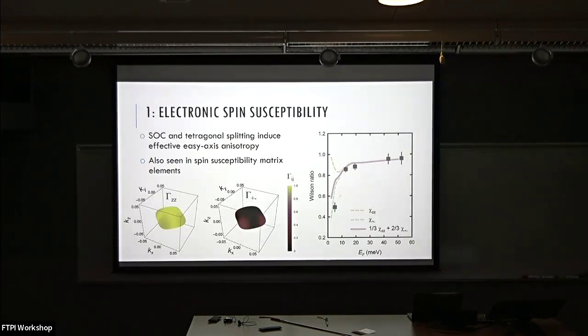Okay, and also you can see this in a very nice way by looking at just the matrix elements in the susceptibility. So here they're projected on the Fermi surface in this low density regime. And again, you can see that for the zz, there's essentially nothing happening. So it's basically 1. But for the transverse one, there's this strong suppression. And actually, as you increase the EF, you can follow how this goes away because the tetragonal splitting goes away. So the tetragonal splitting scale is 10 meV, 100 Kelvin. Once you're above that, this anisotropy basically goes away. So this is really a consequence of this tetragonal splitting.